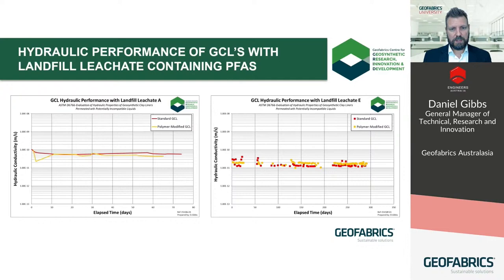And these results are within the bounds of many of the Australian landfill leachates we've tested over the years. So hydraulically, at least, we see that the PFAS itself, and at least at these microgram and nanogram levels, don't appear to affect these GCLs in terms of their hydraulic performance. But what about their ability to trap PFAS?